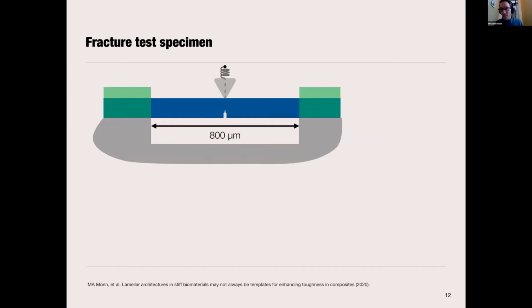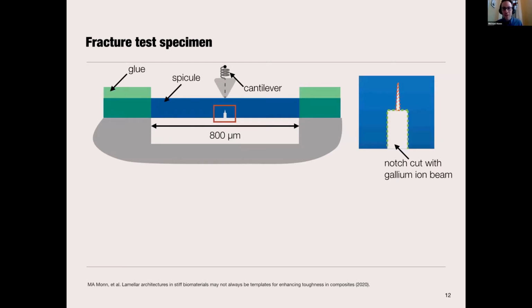So to discuss a little bit more about the specimen, our gauge length is about 800 microns. And if you look, you can see there's a notch cut in the specimen right under the wedge that we apply a load with. And we cut that notch with a gallium ion beam. So you can see two dotted lines here, a green one and an orange one, and we cut it in 2 steps. That's because we were trying to cut rather deep notches. And when you're cutting with a focused gallium ion beam, the gallium ions ablate material, and that material can sometimes redeposit. And we didn't want that, so we started with a wide coarse notch and then created a very sharp notch at the tip.